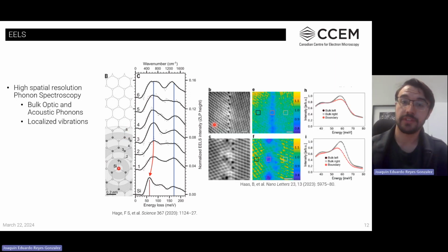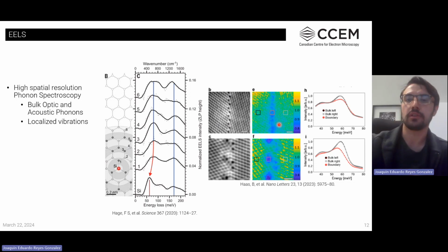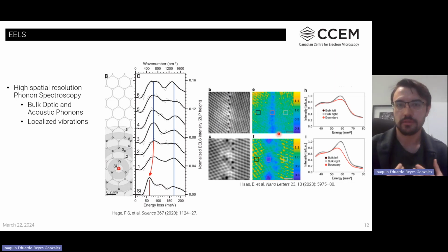Some other structural features worth exploring in semiconductors, for instance, here we have silicon grain boundaries. We have the cases of a symmetric and an asymmetric silicon grain boundary. Again, exploiting spatially resolved maps using STEM EELS, we can have these colorful maps where we identify how the intensity of different phonon modes is distributed throughout the structure, and how some vibrational modes might be suppressed or enhanced depending on the system, at these structural features common in most materials for applications and devices.